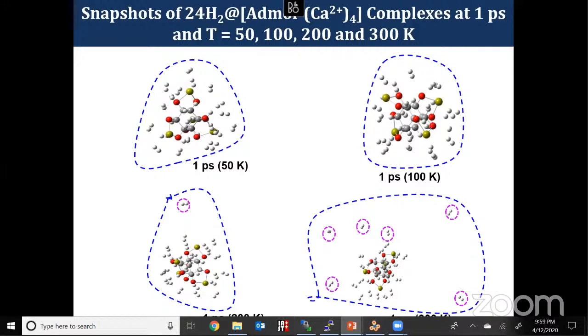So what we observe from this study is that a metal cation with an appropriate substrate, and if possible creating more metal cations on the single substrate, will help to improve the binding energy of the material.